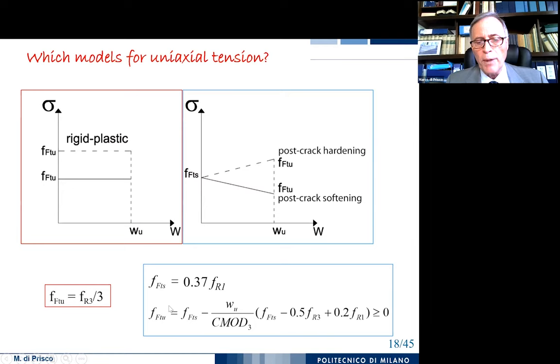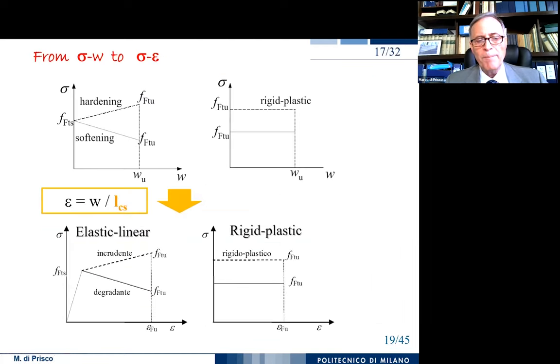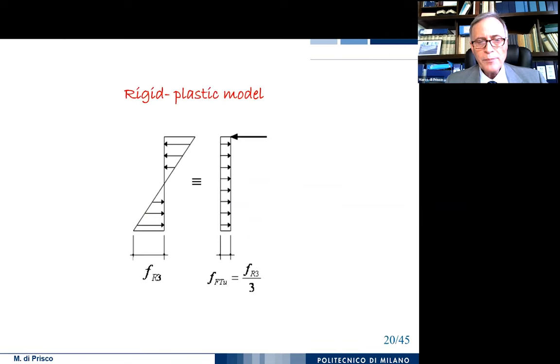And here you see the relationship. How did we obtain this relationship? Always by means of equilibrium. But when we have these two models, we have to pass to the strain. And in order to pass to the strain, as I anticipated, we have to divide the crack opening by the characteristic structural length. So we arrive to introduce these two types of models, which are expressed in terms of stress-strain, so are, if you like, familiar for a conventional design.